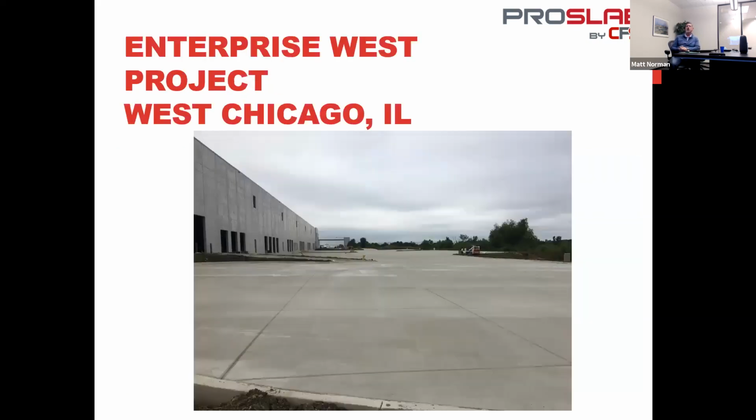Talking about projects, exterior paving is an excellent application for steel fiber reinforcing. This is that Enterprise West project in West Chicago, Illinois that we just completed. It's roughly around 400,000 square feet of exterior pavement. We did not only the truck areas, but we did the car parking areas as well. The fiber dosage was 35 pounds per yard, and we eliminated a number 3 rebar at 18 inches on center in this type of application. Slab thickness for the truck area was 7 inches thick.